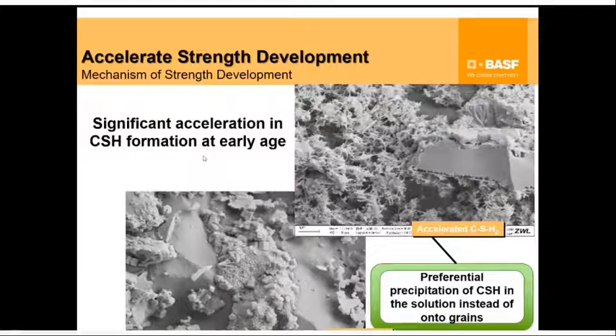The next, this slide basically tries to address this issue of strength development and to accelerate strength development. Now, one thing that one needs to understand in terms of mechanism is that a lot of the setting time and strength development properties are a little different, right? When you're talking about setting time, you're primarily talking about ettringite growth. And this is what controls most of the setting properties over time. And the strength development is governed mainly by the CSH formation and growth properties. So if you want to accelerate set, you can use chemicals that will accelerate ettringite formation. If you want to accelerate strength, you need other chemicals that will actually help a quick or an increased rate of growth of CSH particles.